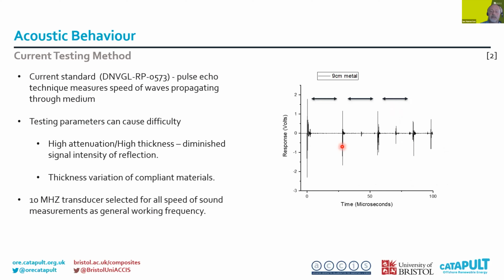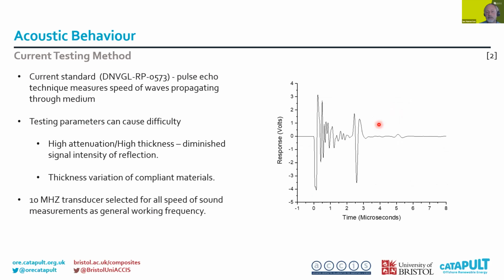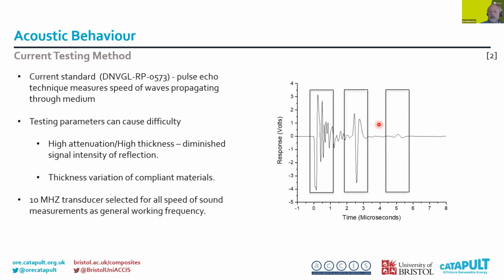You can see a nice clean spectrum where the distance between pulses is nice and clear. As we start to move into viscoelastic materials, on the other hand, these become far more complicated. And if we look at the three areas here, this very complex structure at the center, on the extreme left, is crosstalk. So this is essentially a complication of the signal through the molecular structure. As we increase the thickness of the film, of the protection, then the signal becomes more attenuated, and we start to find it difficult to determine signal shape and position. On the other hand, as we start to go to thinner and thinner structures, then the interference becomes more problematic.